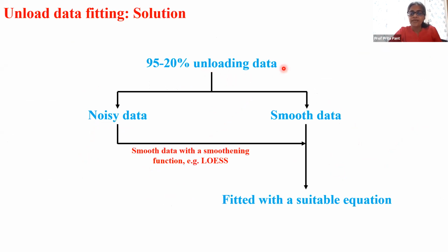do, right? So you take some fraction of your unloading data, and if you have smooth data, you might be able to just fit to it and get residuals distributed randomly about 0 and reasonably small. And you fit it and you're good to go, calculate your S. But you might have noisy data for various reasons, in which case you might want to explore smoothing that data first with a smoothing function.